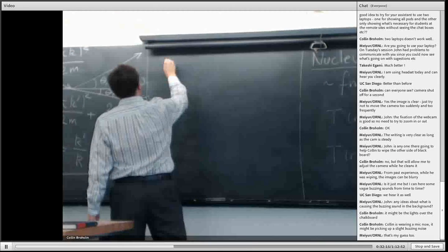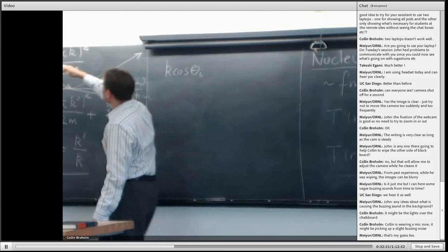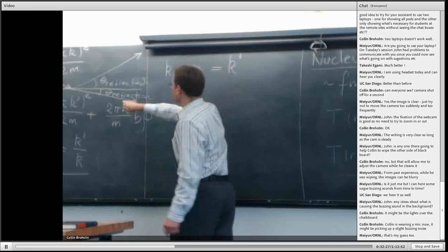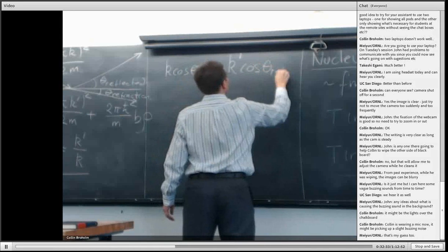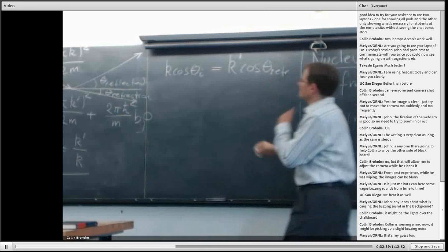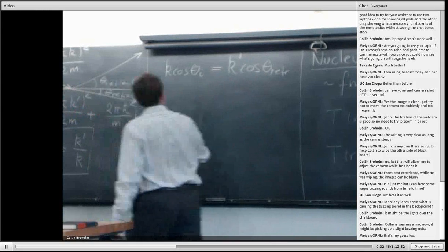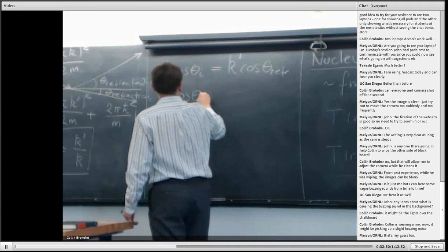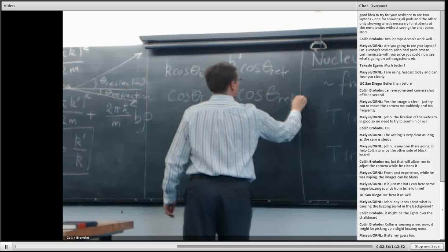It's going to say that k cos theta_I, that's the projection of the incident wave vector onto the interface, has to match k prime, the length of the wave vector in the medium, times cosine theta refraction here. Okay. And as I said, k prime is actually less than k, and I'm going to define this as my index of refraction. So if I divide by k on both sides, I get that cos theta_I must equal n cos theta refraction.